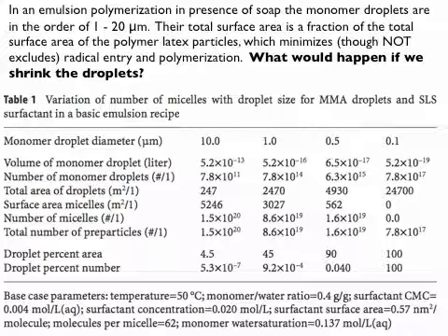So you would get entry into a micelle, and therefore you end up with small particles, also because the number of micelles is very large. So you get exclusive entry into the micelle, so the number of particles you get is roughly the same as the number of micelles you've got. The total surface area of the droplets in this particular case is only 4.5%. So occasionally you might get entry into a droplet, but in most cases you don't.